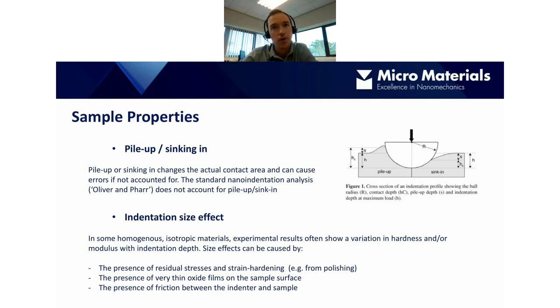You can see on the diagram here, maybe slightly exaggerated, that in the case of pile-up, hc is actually larger than h, the maximum depth. And for sink-in, it's a lot smaller than it would otherwise be. So the standard Oliver and Pharr analysis that I briefly described earlier does not account for these effects. So there are other methods to account for these features.